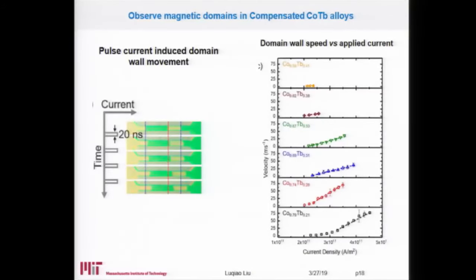Okay, so now what we do is we apply a sequence of nanosecond current pulses onto those micron-sized wires. And what we saw is that the domain edge gets pushed by the current from left to right. After each pulse, we record the magnetic texture image, and we can track the location of those domain wall edges. By summarizing the relationship between the domain wall position and the applied pulse width, we can calculate the domain wall velocity as a function of applied current.